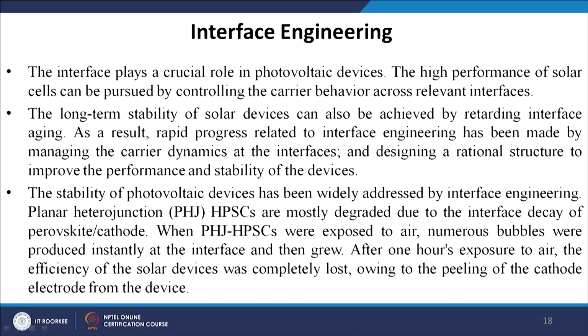When PHJ-HPSCs were exposed to air, numerous bubbles were produced instantly at the interface and then those bubbles grew. After 1 hour of exposure to the air, the efficiency of the solar cell device was completely lost owing to the peeling of the cathode electrode from the device. So, if we expose it to more and more humidity or water vapor, the cathode layer will start peeling up from the interfacial layer.